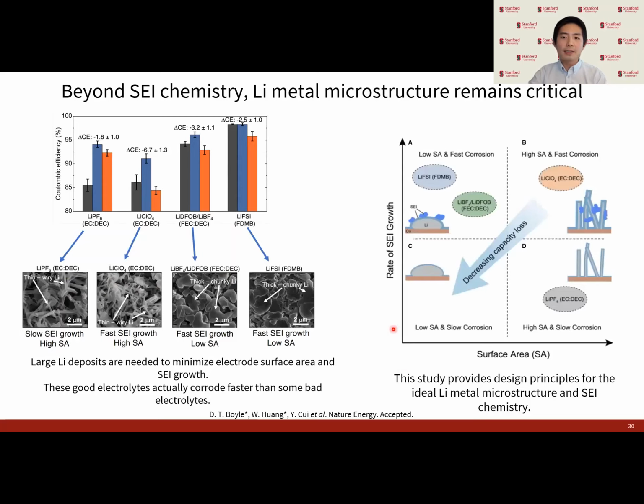So for the field, that tells us that we need to optimize these two factors to ensure long calendar life lithium metal anodes. And that's the surface area of the lithium deposition, along with the rate of SEI growth per surface area, or basically the reactivity of the lithium surface to the electrolyte blend.